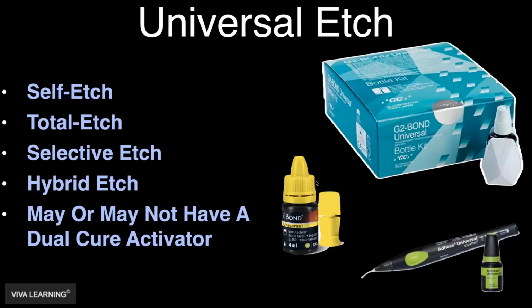The other thing that makes this really unique and also has to do with the pH is that the universal adhesives, the eighth generation, are all compatible with dual cure chemistry. So if you're going to put them underneath a dual cure core buildup or a dual cure resin cement, their pH isn't so acidic that it'll interfere with the chemical polymerization cycle of something that you put on top of it. So it's a really unique feature of this eighth generation. And again, thanks to a very special monomer called MDP, we've got all of these features.